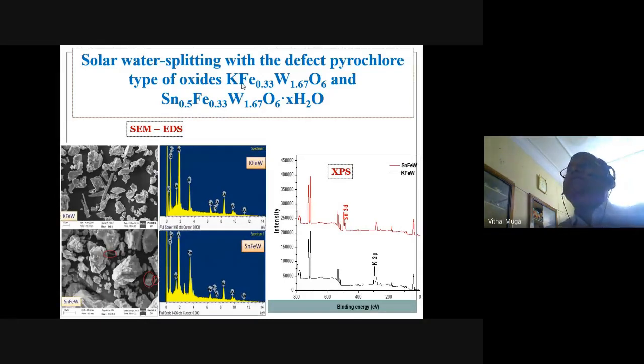gap energy. So what we have done is, this material we prepared, this is a known material, but this is an unknown material. So we replaced with the tin. Now tin has a very important property, because divalent tin has a lone pair of electrons. As a result of that, it will sit at a place above the valence band, and therefore the band gap energy reduces considerably.